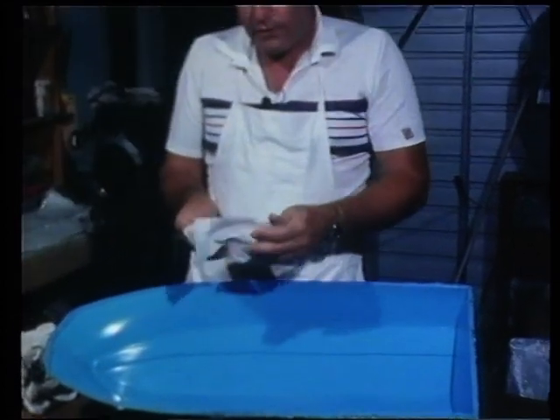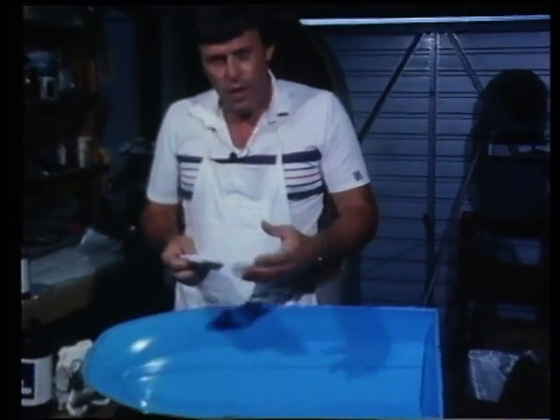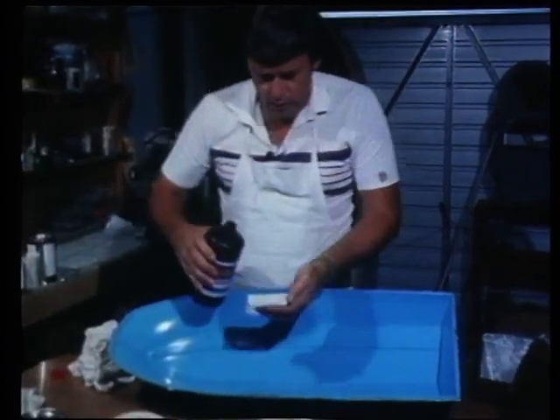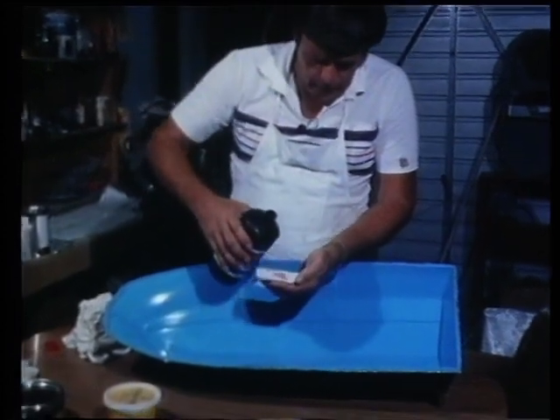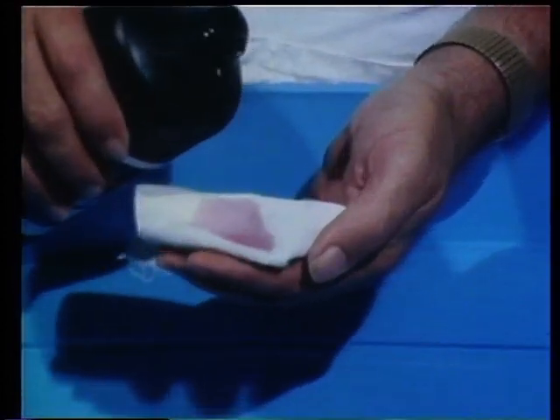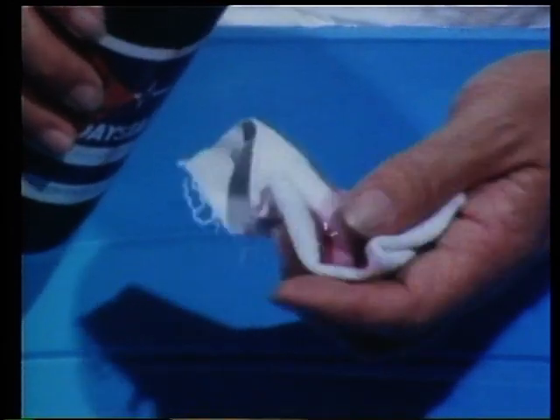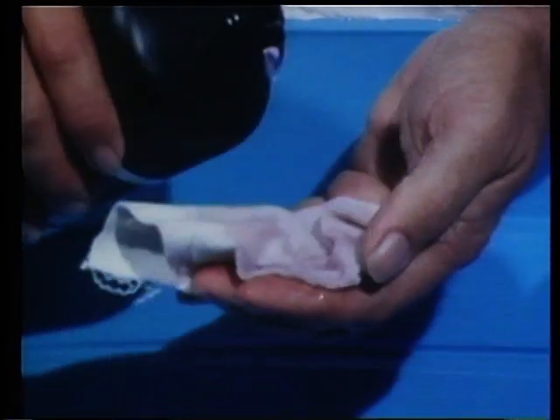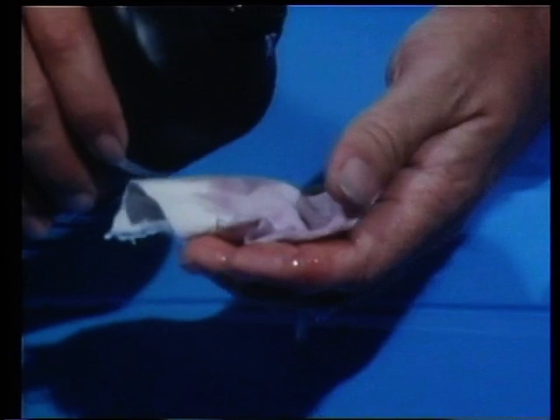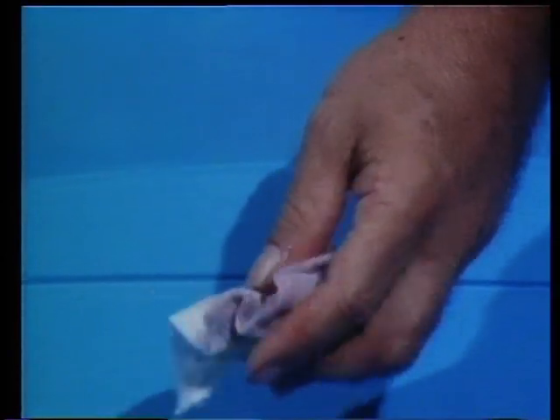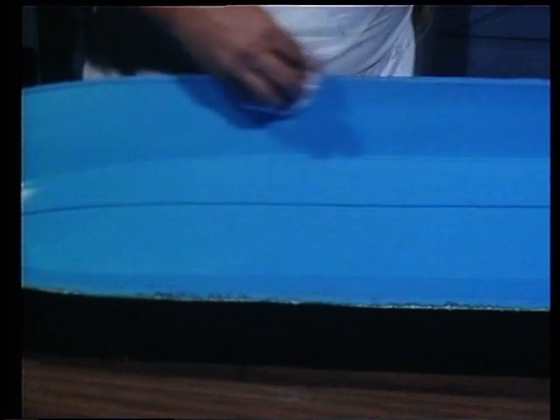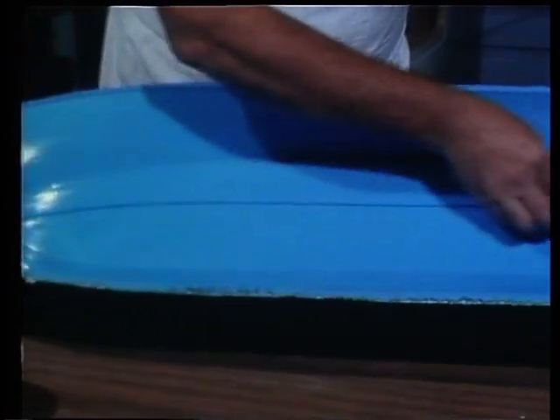Now this is a polyvinyl alcohol, which is a vinyl in suspension in alcohol, and if you look closely there, it's slightly coloured, it has a pink tinge to it, so that it gives you some indication of the coverage that you've achieved. So you quite liberally put the PVA onto the rag and then use the rag to spread it evenly over the inside of the mould, and it really does spread very easily. It does quite a good job of covering the entire surface.